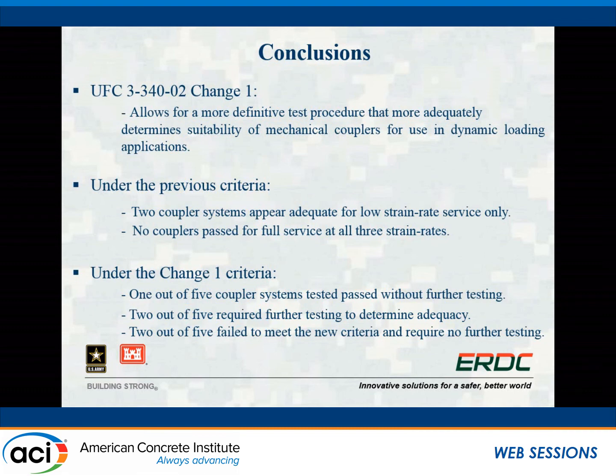So if we look at this Change 1 incorporation in UFC, 1 of the 5 coupler systems that was investigated, that threaded bar system, actually meets those requirements easily. 2 of them had at least 1 test out of the 3 tests that required additional testing, and those were deemed to be adequate. And then 2 out of the 5 systems were deemed to be inadequate and were rejected. No additional testing was required.